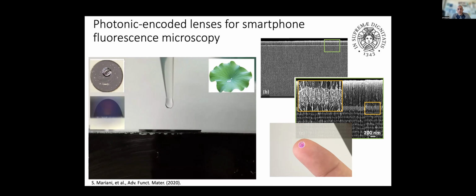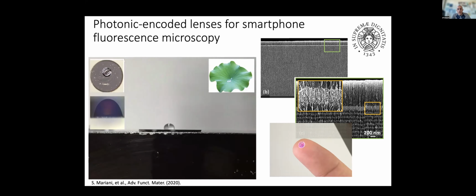a controlled volume of liquid silicone on top of a porous silicon layer, and the silicone, instead of spreading over the surface, just forms a hemisphere, a hemispherical object, like a lens. In this case, we leverage the possibility of controlling the morphology of the porous silicon during the fabrication to do a nanostructuration on the surface like a lotus flower. The lotus flower works for water. In this case, our nanostructuration works for silicone, but the concept is exactly the same.